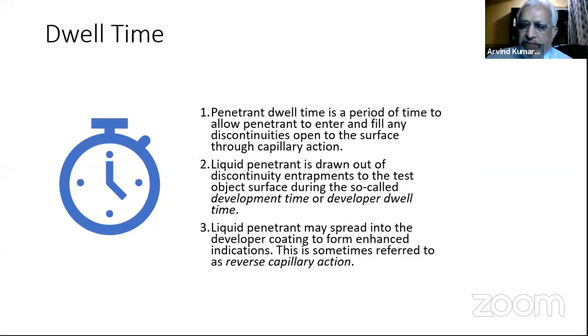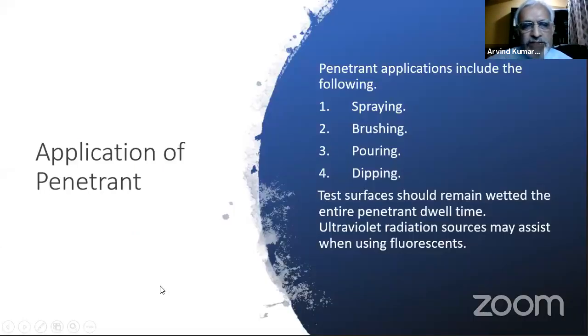Penetrant dwell time is generally for wrought materials, it is specified as 10 minutes. But for other materials, for castings and all, it could be 5 minutes. And for each material, the section 5 gives you what are the dwell times required. But generally it is 10 minutes and 5 minutes. For our application, most of the time it is 10 minutes. Similarly, dwell time of developer also is 10 minutes minimum. And then you can do the interpretation up to 1 hour as per section 5.